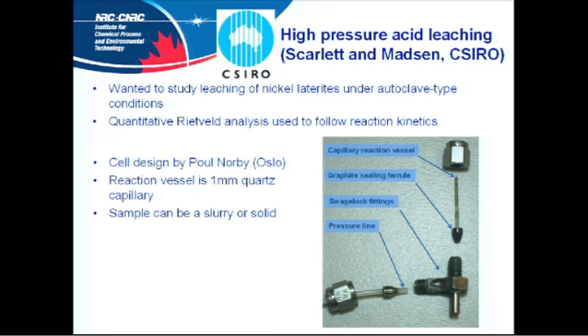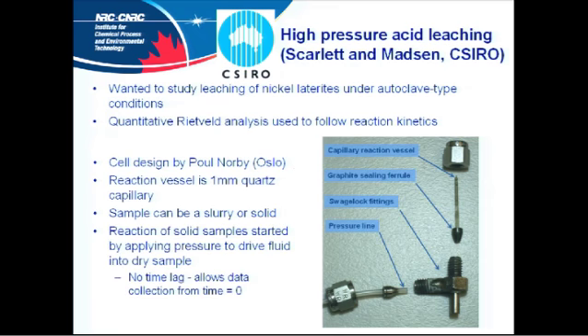And so the sample can be a slurry or a solid. And it actually uses a pressure to drive liquid into the sample to start the reaction off, time equals 0, while it's in situ.